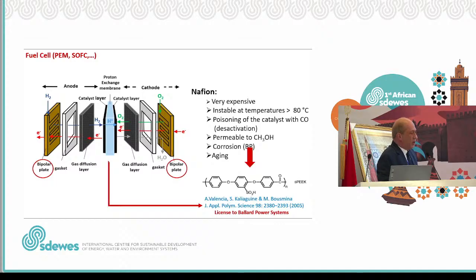PEEK, polyether ketone, with some sulfonated acid groups, and it works a little bit, yet it has problems of aging, it has some problems of working at very, very high temperature, but it's much better than Nafion. And there are other potential electrolytes using some cyclic polymers, some nanocomposites, or some ceramics.